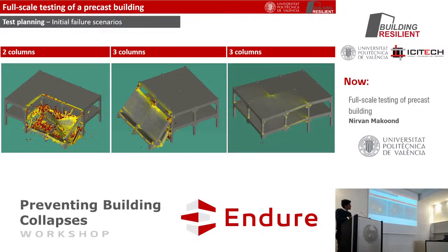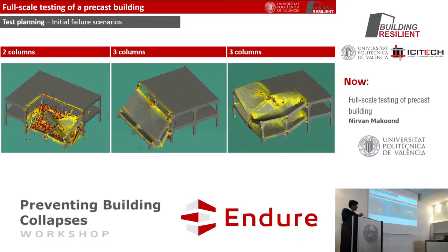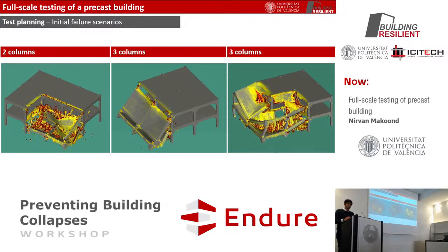So we chose it because it gave us the best margins with respect to the amount of load needed for collapse and the amount of damage needed to initiate the collapse, and also the safety while loading the structure. But also from the scientific point of view, it was more interesting to have failure along two planes to really test how well the segmentation approach was working. Also, our approach we were able to test very well, at least theoretically, based on the connection of the beams and the columns. But we did always have some slight uncertainty based on the topping reinforcement in the other direction as to how that would behave. So we were keen to test it.